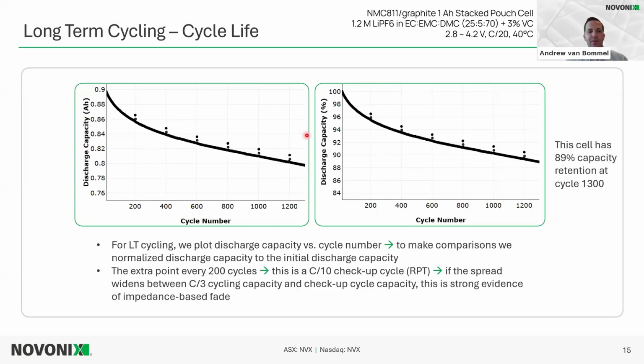And then to make comparisons between different cells, or maybe a cell that was made before that could have slightly higher capacity to start out with, we normalize that initial capacity. So this one is normalized to the start of cycling. So this would be 100% capacity at the start of cycling. And this is the typical profile that we see in long-term cycling.